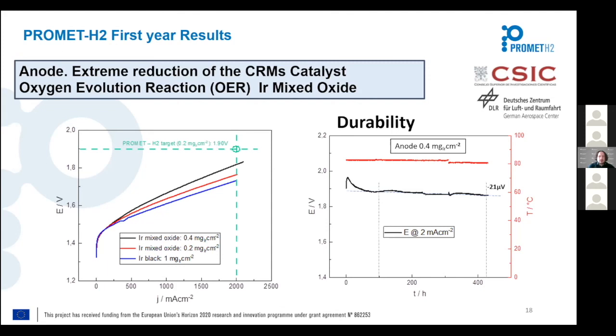Of course, one of the questions here is how durable it is. And then we did a test in MEA, and we observed that these catalysts have a really great durability. We tested almost 500 hours without very high degradation. Then it's one of the most promising catalysts for the moment.